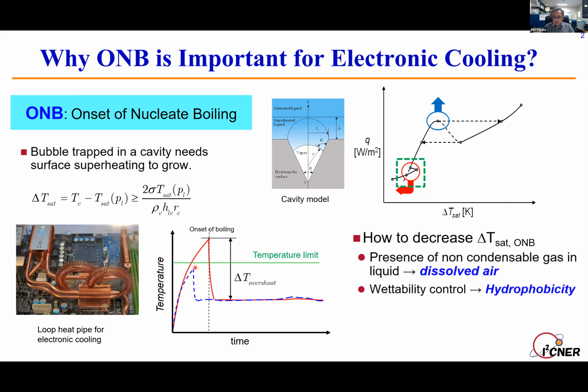Okay. We know how to decrease superheating at onset of nucleate boiling. One method is to inject non-condensable gas in the liquid. If there is dissolved air in the liquid, we have a lower onset of nucleate boiling. The other thing is wettability control. So hydrophobicity works in this case. Especially for the electronic cooling case, if we use water as a cooling fluid, we need to have boiling at subatmospheric pressure, which makes heat transfer work.